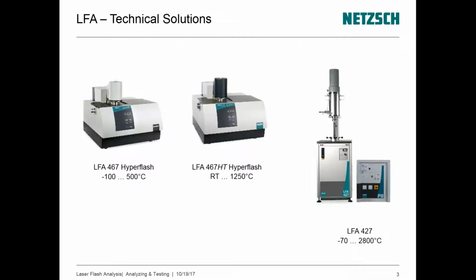So I would say just to start, in terms of LFA technique, our line of instruments splits into three categories or three different instruments. Primarily it depends on the temperature range one wants to perform the measurements. The first instrument, what we call the LFA 467, goes from minus 100 degrees Celsius to 500 degrees. The other one goes to a little bit higher temperature, from room temperature to 1250 degrees, and the last one goes all the way to 2800 degrees Celsius, starting from negative 70 degrees Celsius, and that will be the one we will be primarily looking into as we show data that we obtain on such materials.